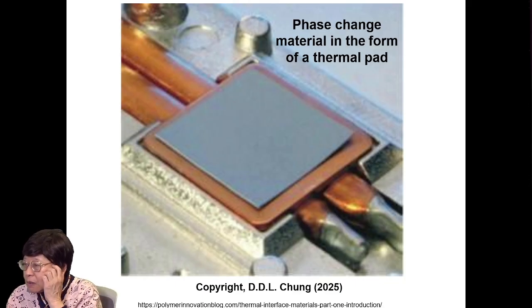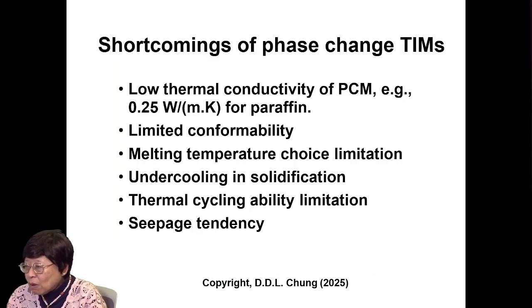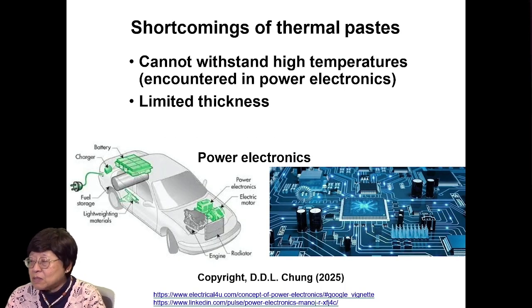Now, phase change material is also available in the form of a thermal pad. Shortcomings of phase change TIMs include these: low thermal conductivity, such as 0.25 watts per meter K for paraffin case, limited conformability, melting temperature choice limitation, undercooling in solidification, thermal cycling ability limitation, and seepage tendency. However, shortcomings of thermal paste are these: they cannot withstand high temperatures, which are encountered in power electronics. Also, limited thickness.